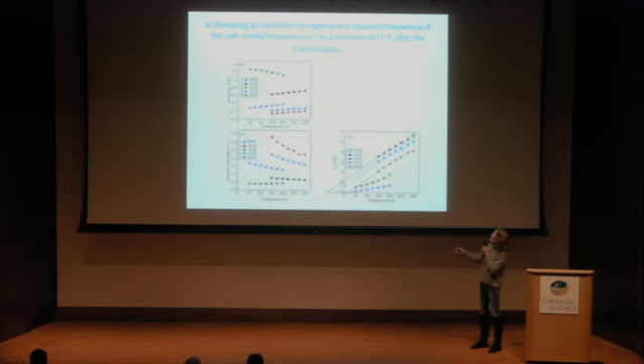So you see here the damping as a function of temperature for the 5 compounds. In agreement with experimental data, the damping in lead titanate grows when approaching the phase transition temperature. Europium titanate has an almost temperature-independent damping, whereas these two are close to the other 4 compounds. So this is the exception, which tells you about the first-order nature of the phase transition. Then we come to the oscillator strength, which is increasing with decreasing temperature, not for barium titanate and europium titanate. And here's the soft mode frequency as a function of temperature, and you see these 3 extrapolate to 0 or to negative, respectively close to 0 temperatures, whereas these go to 0 at the phase transition temperature.